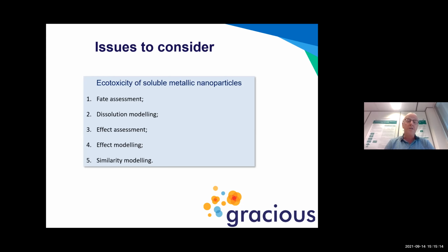Dissolution modeling as second step is part of that fate assessment, and this is especially assessing the kinetics of dissolution so as to be able to determine the concentration of particles and ions over time. Third step is the effect assessment. That is actually performing the ecotoxicity testing of the suspensions of the nanoparticles over time.